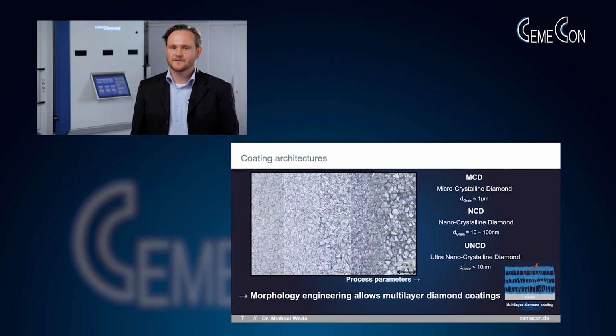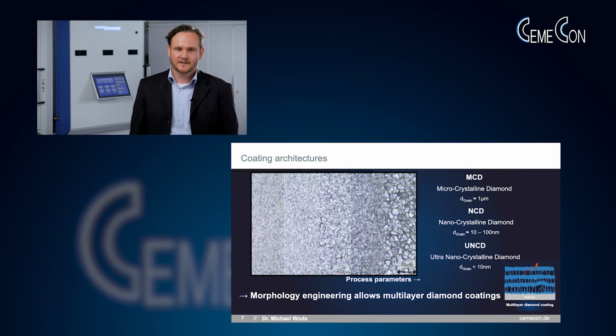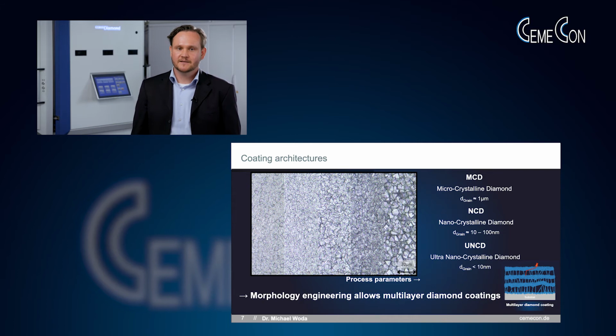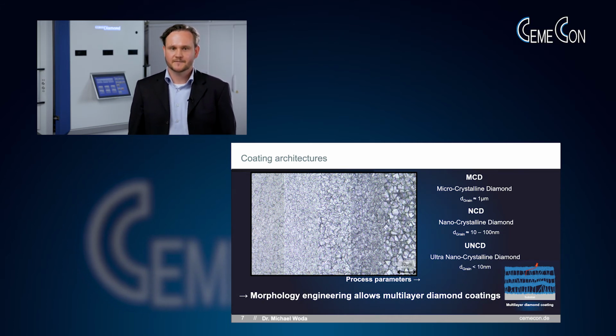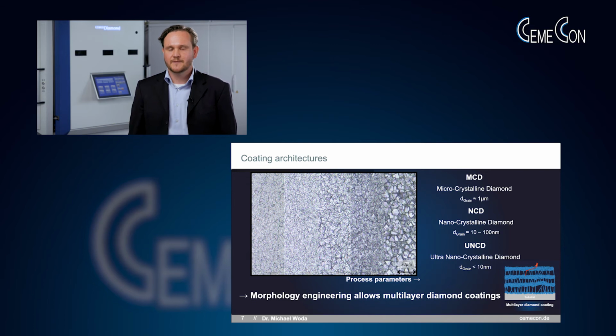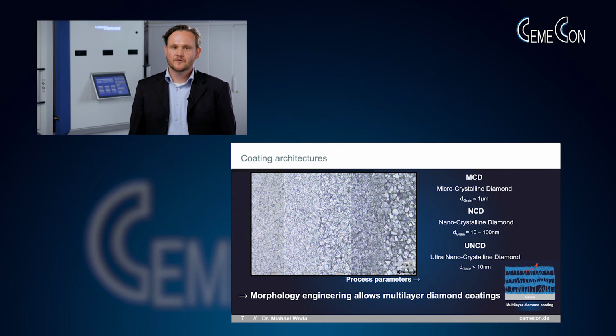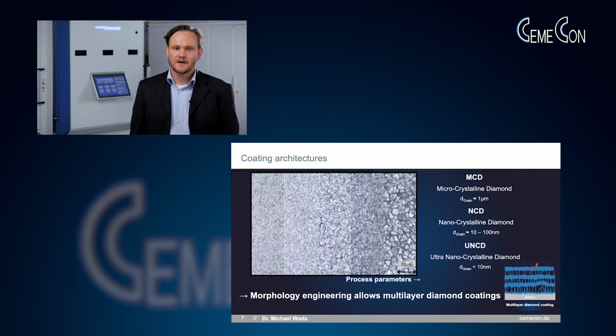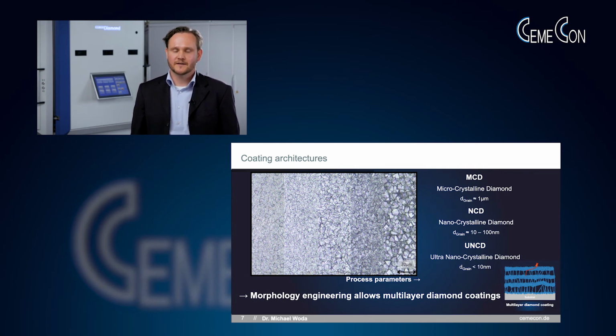We can now wonder what type of thin films we want to coat and what we are able to coat. By tuning the process parameters like gas composition, temperature, or pressure, it is possible to tailor the morphology of the thin films systematically. An example of such a coating morphology series is shown here. Commonly, diamond is classified into three different groups. With grain sizes of about a micron or more, we've got microcrystalline diamond. We can reduce the grain sizes to some tens or hundreds of nanometers, ending up with the so-called nanocrystalline diamond, or we can reduce the grain size to sizes below 10 nanometers, where we have the so-called ultra-nanocrystalline diamond.